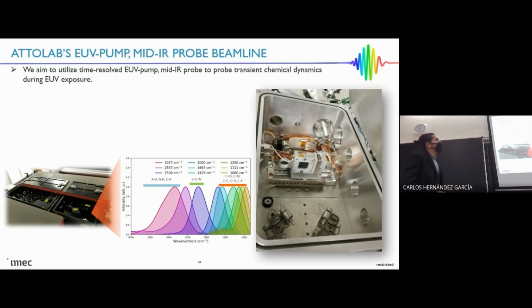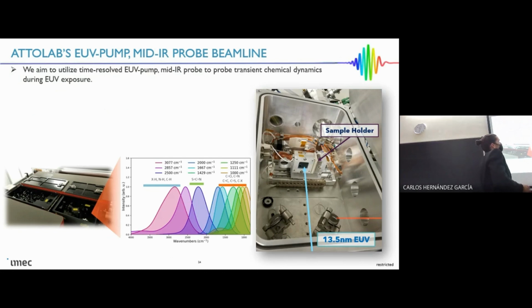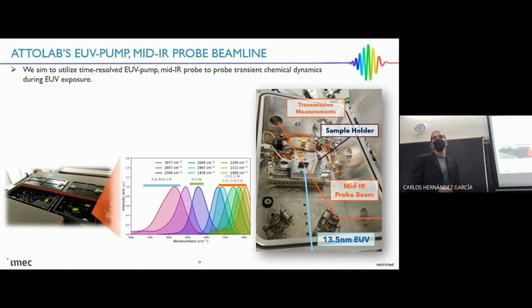And at the same time, we have a sample chamber for this, which is quite straightforward. It holds small pieces of those big wafers I talked about earlier with photoresist on them. We excite with 13.5 nanometer light. And then we have 2 ways that we can do the spectroscopy. One is through transmission measurements to go through the bulk, because silicon is transparent to mid-IR. And then we can also do reflection if we suspect for any reason there's a surface